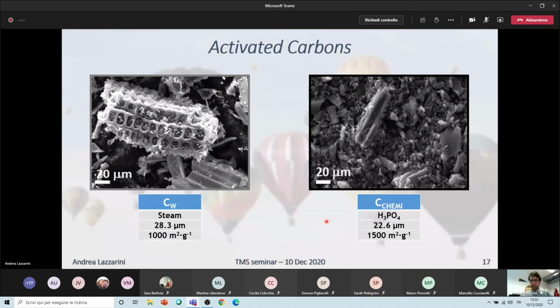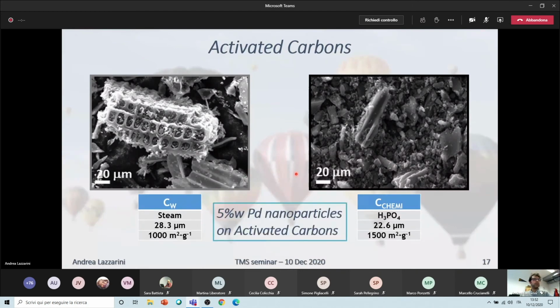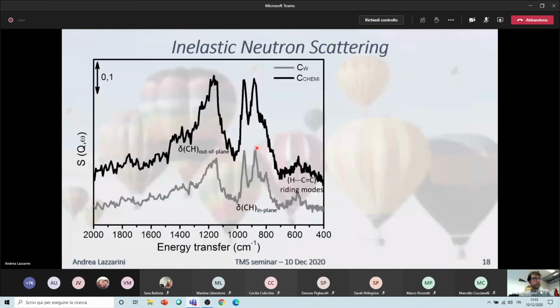With this, they were produced with 5% weight palladium nanoparticle catalysts; these particles were deposited onto the surface of these carbons. So my goal was to characterize thoroughly these two systems and to see if the differences among them can provide an explanation for different catalytic activities. Being carbon black and difficult to study with spectroscopies based on light, the natural choice was using neutron spectroscopy, that is sensitive mostly, and only, to the hydrogen terminations that are present in the systems.